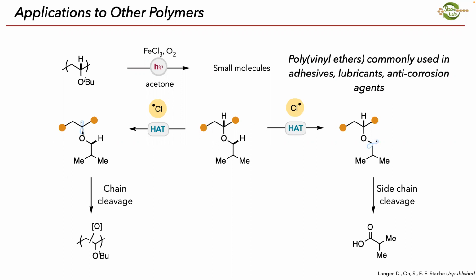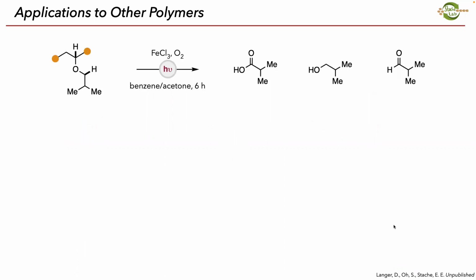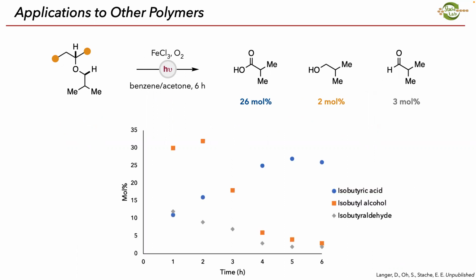And we can activate the backbone using chlorine radical, which we can get chain cleavage, or we can activate the side chain, and then we can get cleavage of the side chain to get these oxidized small molecules. And so there's 2 different pathways we can go through. And so what he found, he tracked down these different molecules, again, using GC, and found about 30 mole% total of small molecules. So 30% of these repeat units were being converted. And interestingly, what he saw is that at earlier time points, we actually have a much higher yield of the products. And so we have 30% of this alcohol shown here at 2 hours, but it starts to decompose over time and turn into this carboxylic acid.